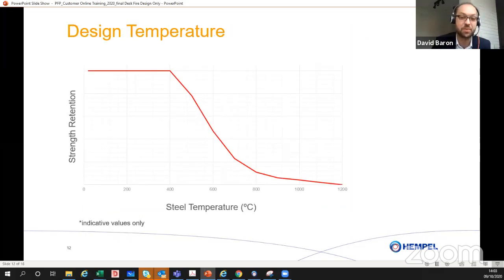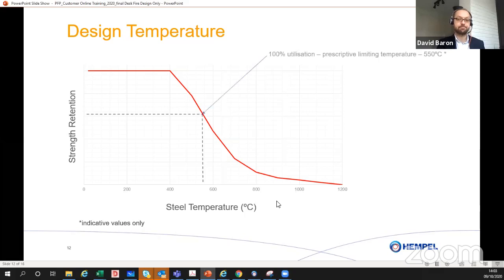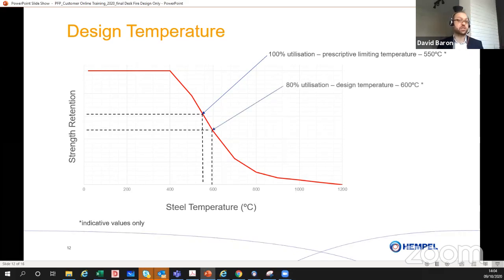Well, one of the first slides you were shown in the presentation was this concept that steel loses strength at elevated temperatures. And on the left axis here, I have the strength retention again, and on the bottom axis, the temperature within the steel. So as a designer or as a manufacturer, if we know nothing about the structure, we would assume 100% utilization and default to the prescriptive limiting temperatures. So in this case, 550. And please note that these values I'm showing are indicative, just to show at a high level the concepts behind the fire design approach. But if I was told by the structural engineers that the structure actually wasn't loaded beyond 80% of its utilization, the design temperature would be higher. This is because there is more capacity left within the steel, so you can allow the steel to get a bit hotter. And again, if the steel was only stressed to 60% of its utilization, the design temperature would increase because of that extra capacity within the steel.